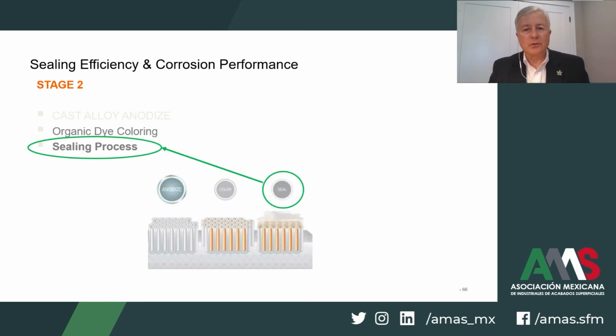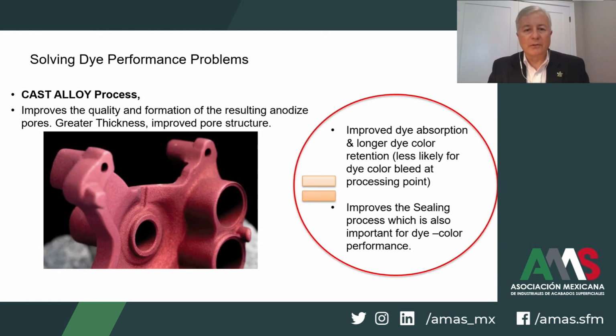Using stage 1 and stage 2 cast alloy processing improves the sealing performance. The proper sealing of any anodized oxide is the critical part of the success for its intended application. So the sealing steps impact the color performance, but also are important for realizing the best corrosion performance from the anodized oxide coating process. Especially for high silicon casting alloys, higher efficiency sealing improves the performance of the dyes, and it overcomes some traditional problems with the dye process for anodizing. Improvements include longer dye color retention in service, but also improved dye absorption and less dye bleed during the processing of the cast part, which is important for the anodizing plant.